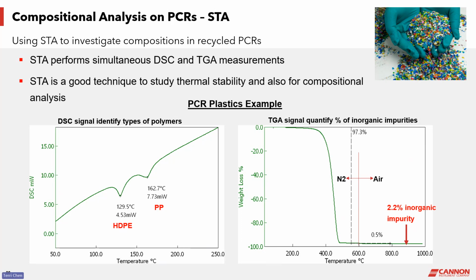Through a simple temperature scan measurement, the STA DSC part of the signal identified 2 melting peaks, which correlate to the melting of HDPE and PP. From this part of the results, we can say that this PCR batch mainly contains HDPE and PP.